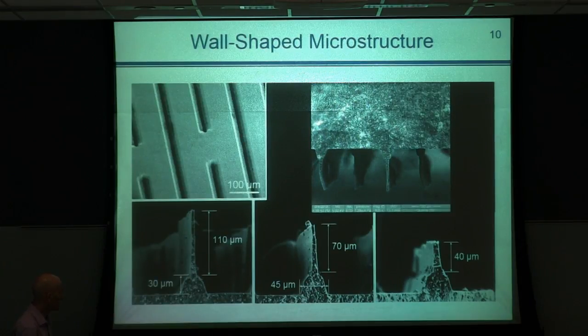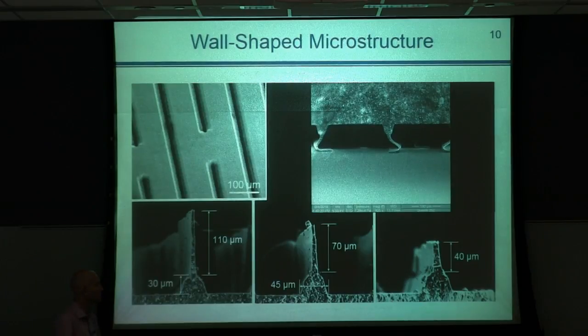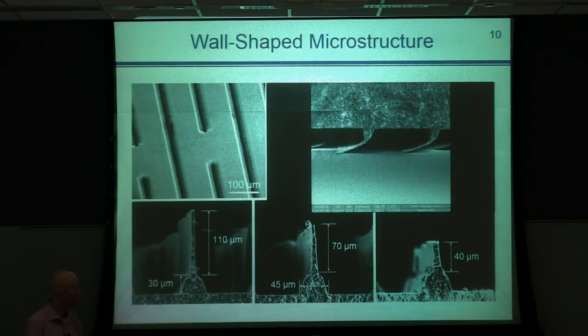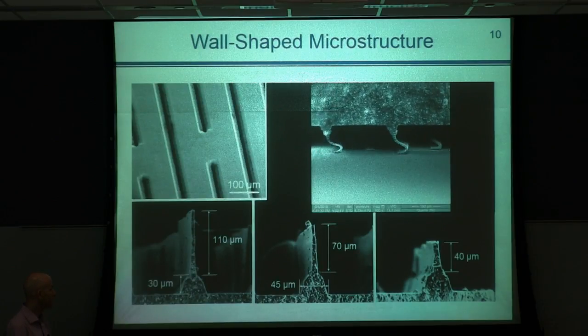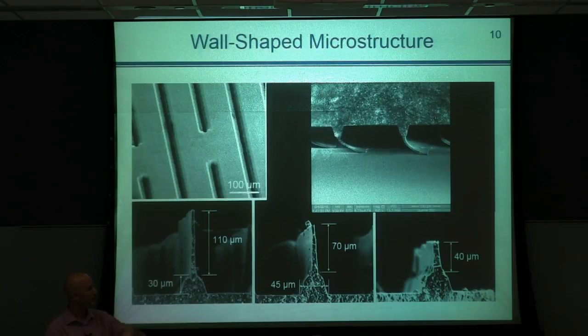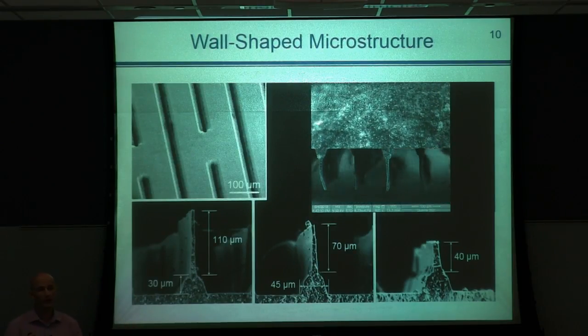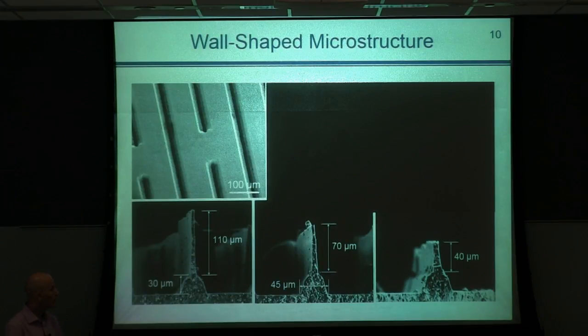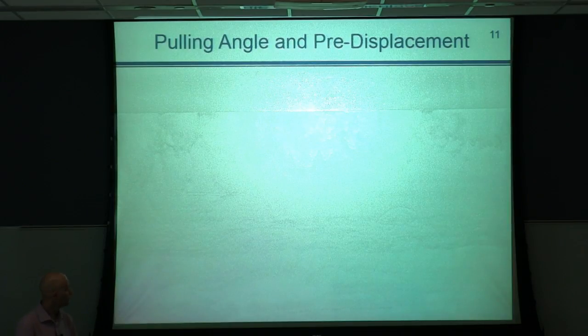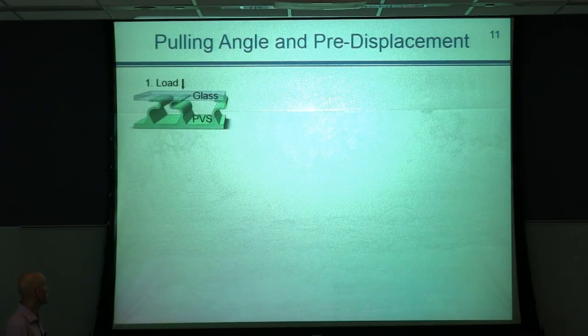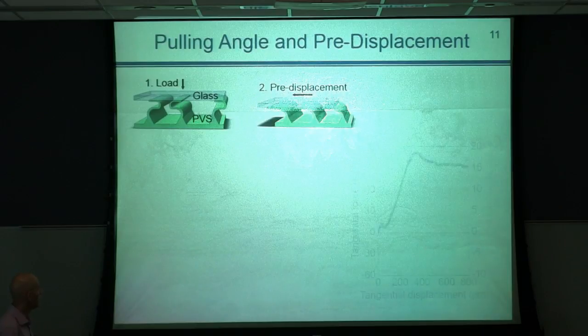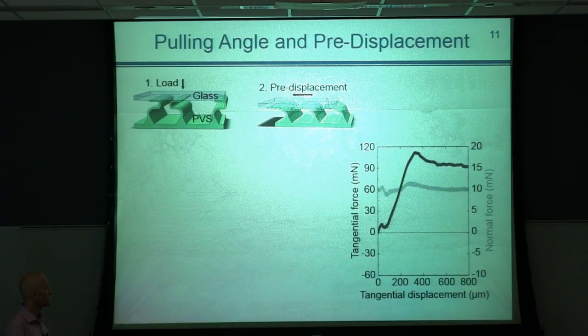And this is a short video filmed in the SEM that represents how the structures operate when they are loaded in the normal and then in the lateral direction on two opposite sides. So you can see how these structures can invert themselves and attach themselves properly to the counterface. So in order to test their operation, we first focused on verifying the idea that pulling angle is indeed an important parameter. So we designed the test in which the surfaces were loaded normally this way until a certain very light load was achieved. And then we applied tangential displacement to align all these structures in the same direction.